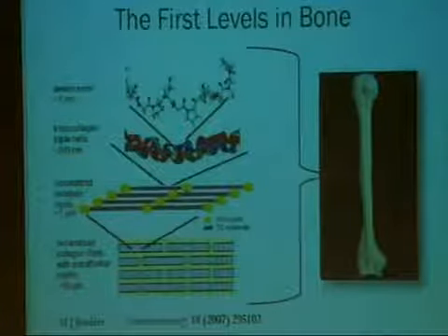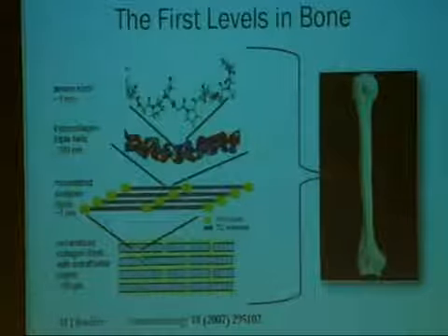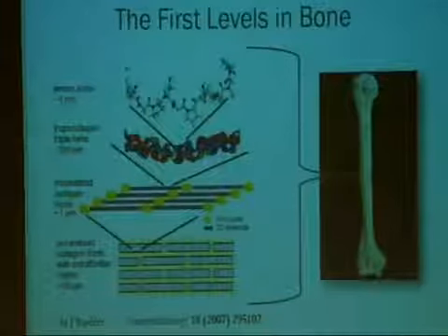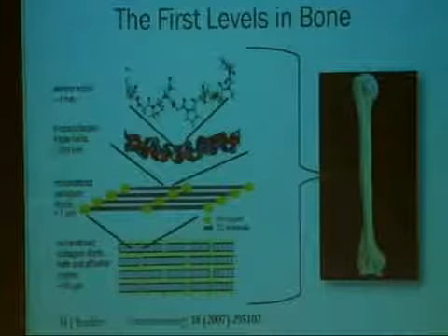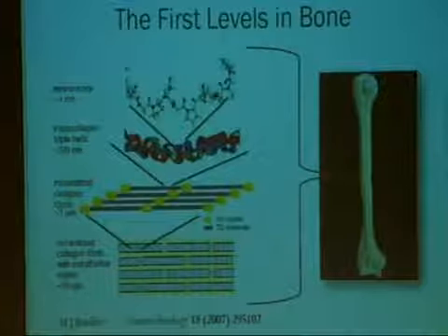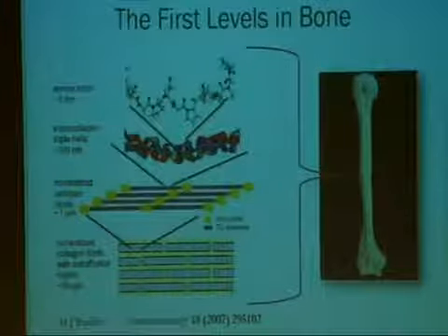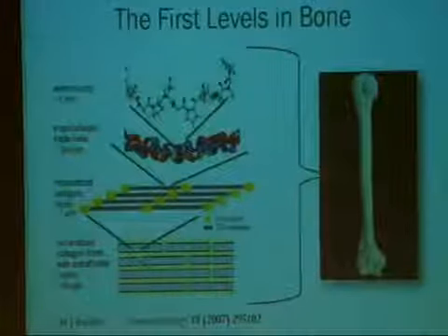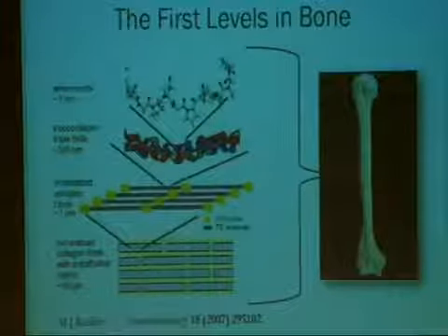And then when these collagen proteins assemble in staggered arrays, they form the collagen fibrils. And in the gaps between the collagen fibrils, there is a mineral phase of hydroxyapatite. The last structure that is found in all types of bone is bone fiber, which is basically, again, those mineralized fibrils staggered in arrays, and in between them there's extrafibril matrix of protein.